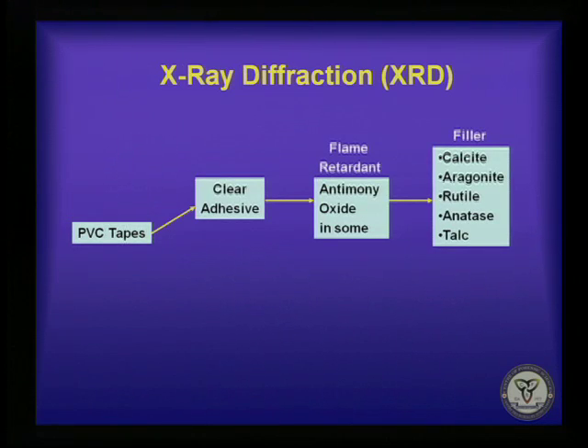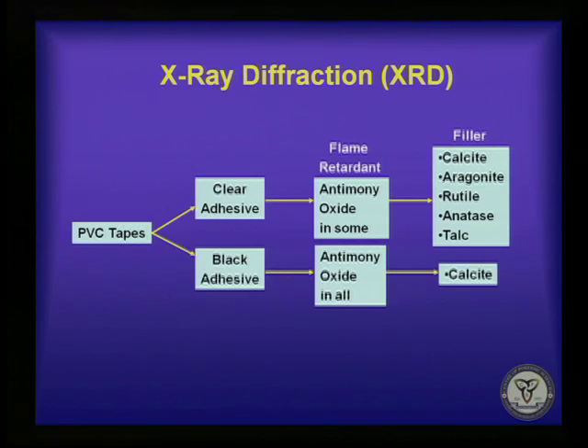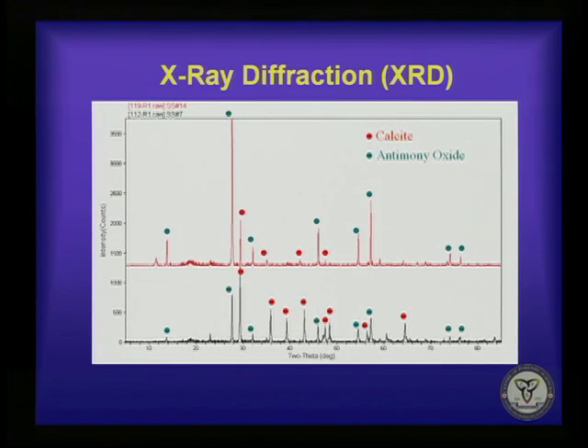X-ray diffraction for the tapes with the clear adhesives, we saw antimony oxide, which is a flame retardant. It was present in some of the tapes, and then we saw a combination of the fillers, so calcite and aragonite forms of calcium carbonate, rutile and anatase forms of titanium dioxide, and talc. And for the tapes with the black adhesives, we saw antimony oxide in all of the tapes and calcite in some. And here are two diffraction patterns. The top one has more antimony oxide compared to calcite, and the bottom one has more calcite compared to antimony oxide. So these both have the same components, but they're present in different amounts.